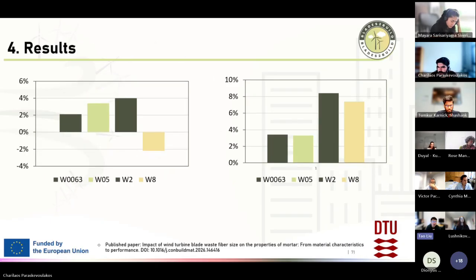And then we see the different sizes of the blade waste. The W means turbine blade waste, and the numbering afterwards is the size of the blade waste. 0.063 is 0.063 millimeter, 0.5 is 0.5 millimeter, 2 is 2 millimeters, not micro, and 8 is 8 millimeters. We can see that from the compressive strength, they can help with very good compressive strength. And the flexure strength, as we know, if you do the fiber reinforcement, the flexure strengths are also increased. From both cases, we know that around 2 millimeters is a very optimum performance, whether the compressive or the flexure strength. So next slide, please.